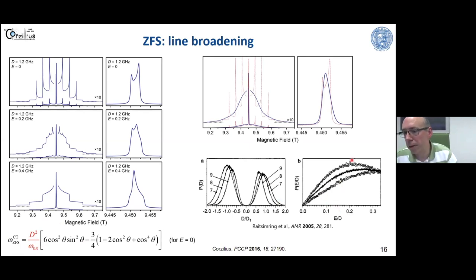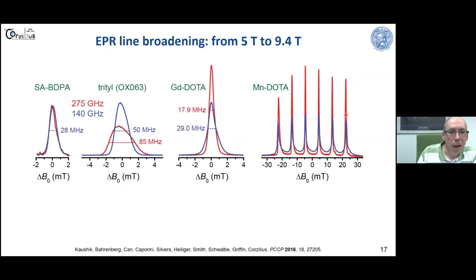And these are more or less derived experimentally or by MD simulations, and they match pretty well. And this means you usually cannot observe these distinct features in frozen solutions, but you have a more or less smooth background of the satellite transitions, and also a much different shape of your central transition. And here you can see in a practical outcome the broadening due to the second order effect.